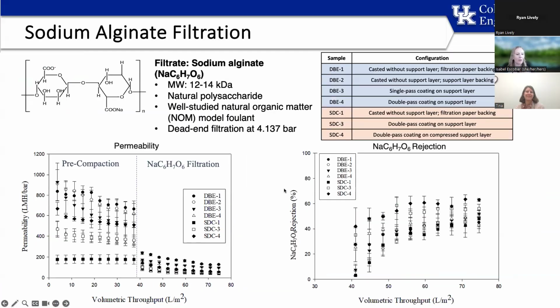We then used our second substrate, which was sodium alginate. This is primarily because it tends to stick more to the membrane. We again performed pre-compaction. We saw a little bit more variation in the permeability, but again, all of them showed pretty high permeability levels. Rejections were lower. Obviously, we chose sodium alginate because it's more of a foulant. It represents natural organic matter more, and it has a wider variety of sizes. And we had, as expected, a much wider variety of rejections, but that SDC3, that pre-treated slot die coating membrane, did perform very well in both.